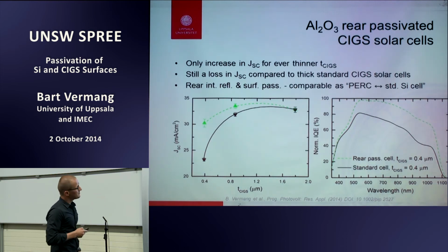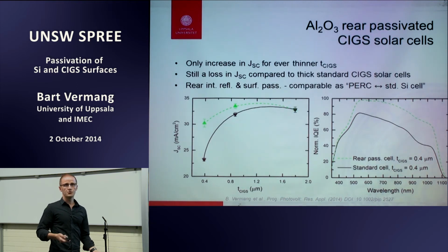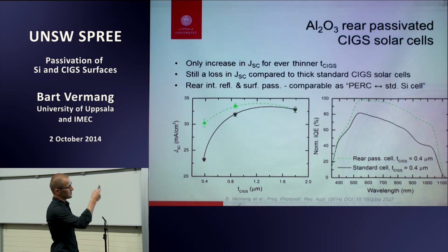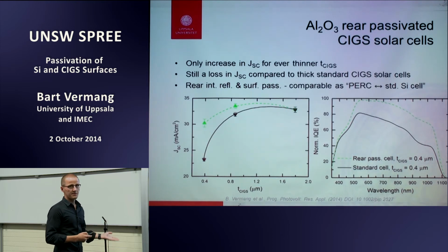If you look at the IQE as a function of wavelength, for a very thin cell, a cell with only 400 nanometers of CIGS, where normally in industry it is 2 to 3 micron, then you see for a thin cell unpassivated, which is the black curve, you lose a lot of collection everywhere. While if you have the passivation layer, you collect more because of rear reflection, which we have been calculating already for the aluminum oxide passivation layer and also measuring, but also because of the passivation. It's so thin that you feel everything within the absorber layer.